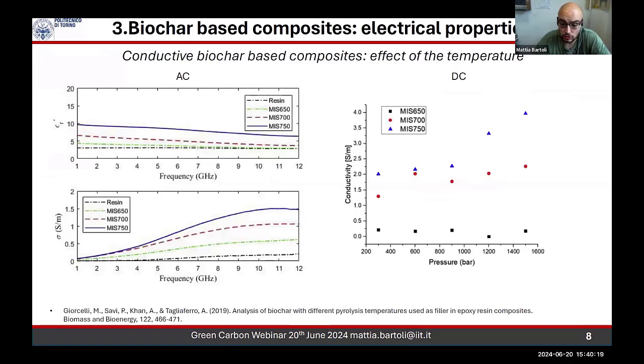And here you see that temperature, as I said, plays a great role. If you are just moving from 650 up to 750, the electrical performance, both in frequency, so under microwave radiation, and under simple compression, just to check the conductivity under stress conditions, you see that 100 degrees matters a lot. But this temperature is not enough for certain kinds of application. It was, again, a very old study, 5 years old now. But that study helped us to understand that we should push the temperature.